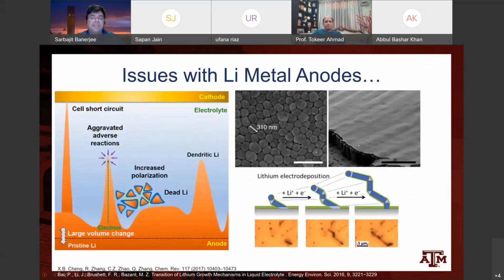So here's a SEM image of columnar lithium electrodeposition. That's what the dream is. You want to have this take place over hundreds of cycles, a few thousand cycles, without having dendrite formation, but it's very hard to prevent this. And this graphic here schematically illustrates a lot of the challenges. So lithium is a conversion electrode, unlike graphite where you've got a host. So the large volume change that happens can result in dendrite formation, and the dendrites that can form can go all the way across the cell, resulting in a short circuit. That's of course the most catastrophic thing that can happen.